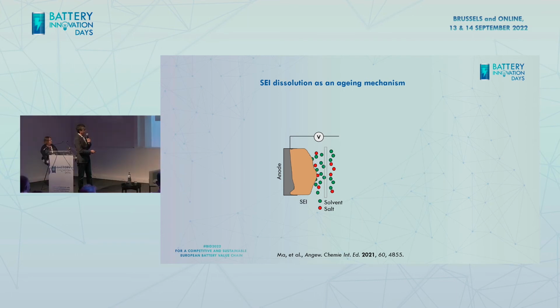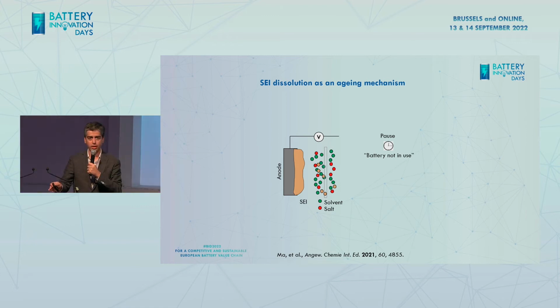What we have been trying to understand is what happens to this layer at pause time, with no electrochemistry. You form this layer and just wait for some time to see what happens to it. What you don't want is to see this layer gone. By gone, I mean it can be dissolved in the liquid electrolyte, or it can be decomposed to other species. So we try to understand this storage time. In a real application, you might see this as capacity fading during the shelf lifetime, or you can say it's self-discharge, so the battery will be discharged by itself with no external current or potential.